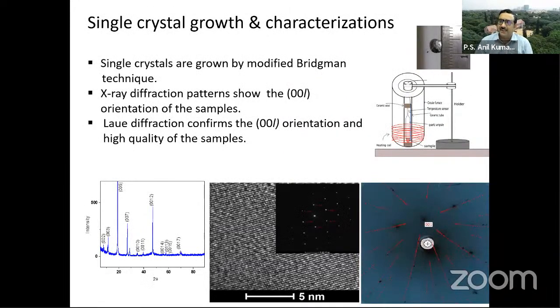We grew these materials by the Bridgman technique, and it takes around 15 days to grow one crystal. So we have to do several trial and errors to get a proper good crystal. This is the example of the X-ray diffraction of this material. This shows all the 00L orientations. We also did high resolution transmission electron microscopy as well as Laue diffraction to find out the single crystal nature of this material.